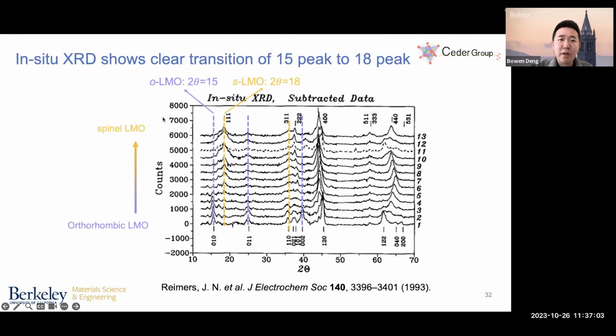And the in situ XRD studies done in the early 90s show a clear transition from the initial orthorhombic characteristic peaks at 2 theta equals 15 degrees to the final spinel characteristic peaks at 2 theta equals 18 degrees, which resembles this phase transformation from the orthorhombic symmetry to the spinel symmetry.